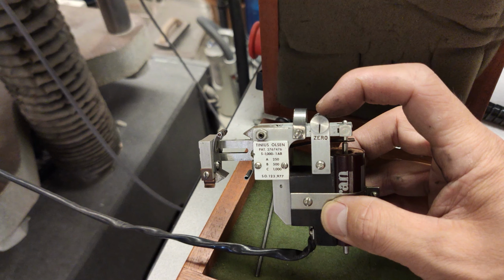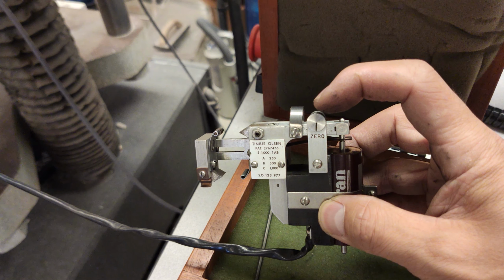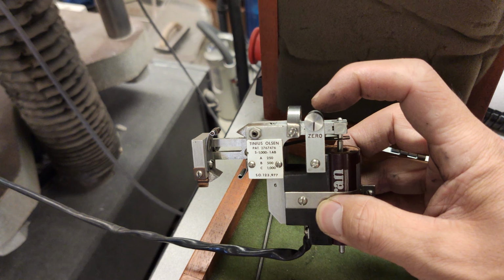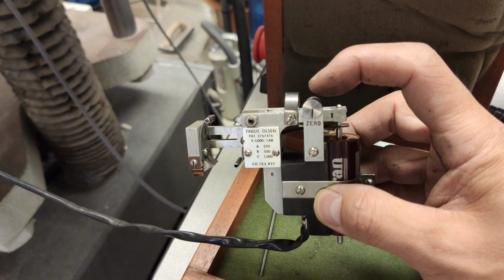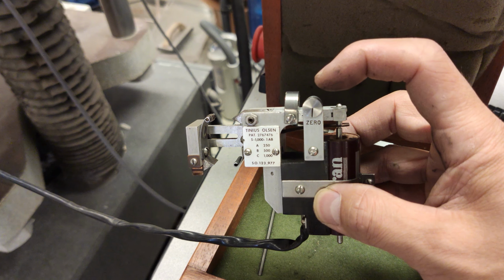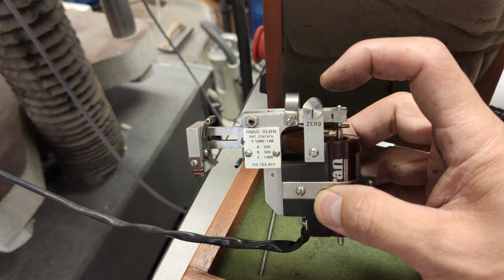Besides the UTM, we also need a extensometer to measure the strain during the tensile test. Here is a close look at the 1-inch gauge length extensometer. It has a rotary knob marked as 0. This is the lock to fix the arm on the top of the extensometer to the initial position. It means that at the time we grab the extensometer on the testing sample, the initial measuring length is assured by this lock to be exactly 1 inch.